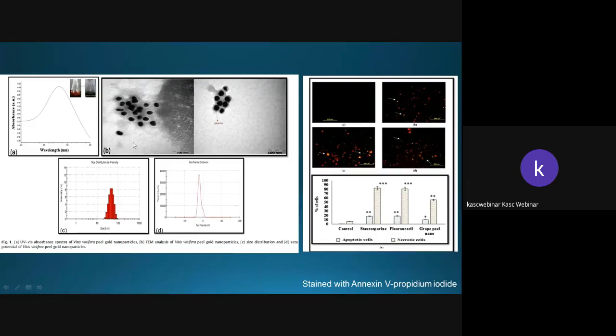So the TEM analysis revealed the core size of the Vitis vinifera gold nanoparticles to be 20 nanometers to 40 nanometers in size with a spherical morphology, predominantly confirming the formation of gold nanoparticles. So they showed a thin layer of Vitis vinifera around the gold nanoparticles, which might have provided stabilization and acted as a nucleation site. And for the size distribution, the hydrodynamic size of the particles ranged from 20 to 80 nanometers with a mean diameter of 52 plus or minus 6 nanometers.